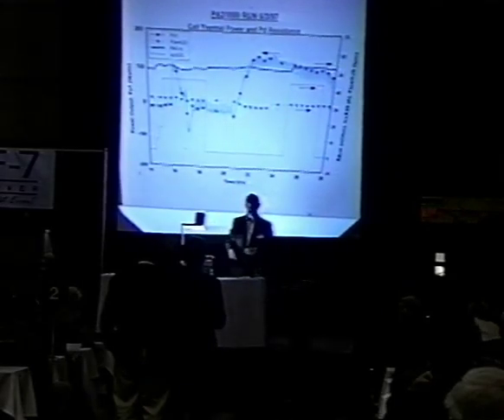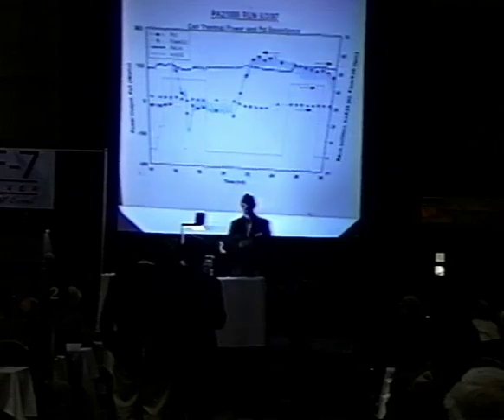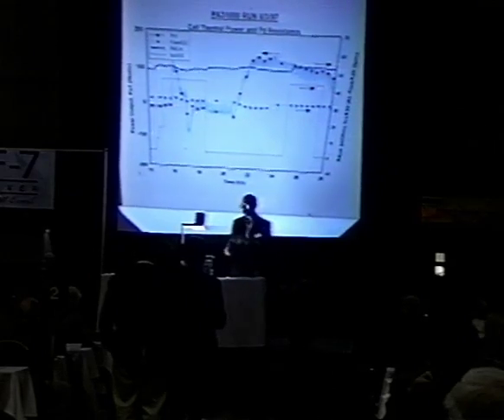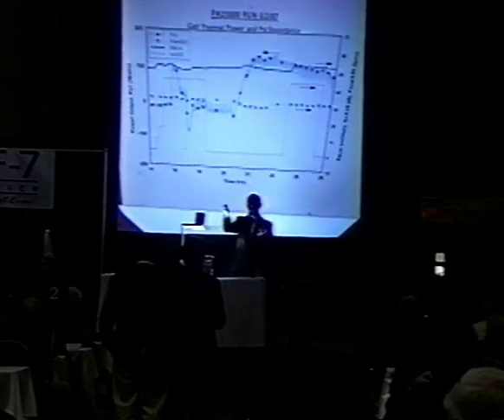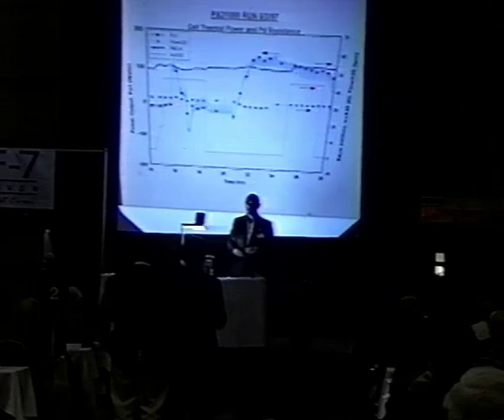That's artificial. All I did was cool the cell. When I cooled the cell down from 60 degrees to 10 degrees centigrade, I took heat out of the cell. So therefore, the power signature goes up just because the temperature is reversed on the inlet and outlet. That's a very good question. It's quite confusing. Did I answer it pretty well?